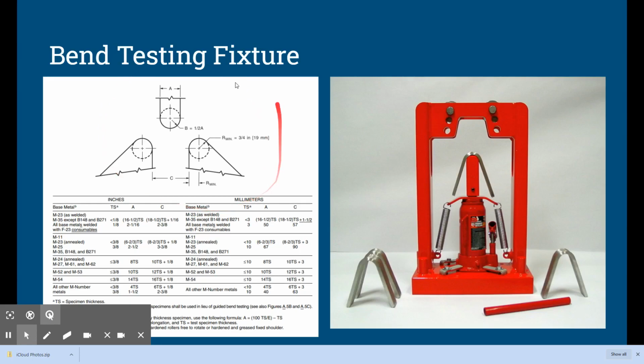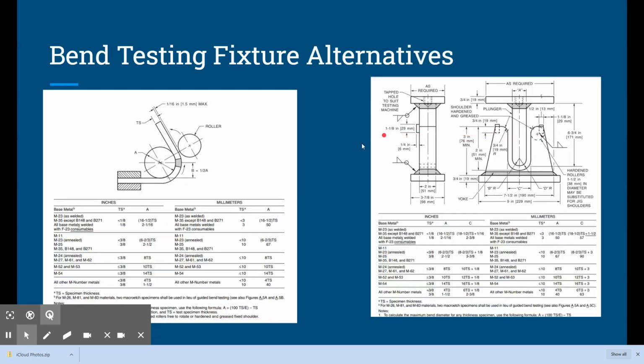There are very specific standards for how those bend test fixtures look and how they operate in terms of the diameter of the roller, the distance apart. You can see this one's adjustable for doing different thicknesses. And so here's what we use. There are some alternatives, and we could do a bend where we wrap it around a center point. So if you've got a Di-Acro bender, you could rig up something with that. You just have to follow the standards. There's also a plunger type. So if you already have a hydraulic press in your shop, you could fabricate something or buy just the fixtures themselves to slide into your hydraulic press, and you could bend your coupons that way.